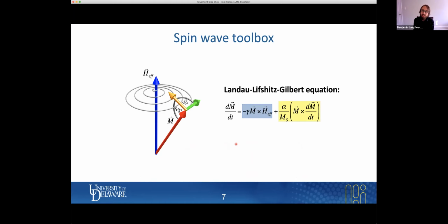This precessional motion is governed by the Landau-Lifshitz-Gilbert equation, so that is the fundamental equation of motion of the magnetization here shown in red, under the influence of an effective magnetic field. So this is shown here in blue, and that contains the external field, microwave magnetic fields, anisotropy fields, dipolar fields, whatever you have, okay? And this first term here, this first torque is M cross H effective. This is the driving torque term illustrated by this green arrow. And as a result of that, the magnetization starts to precess. Gamma is the gyromagnetic ratio.